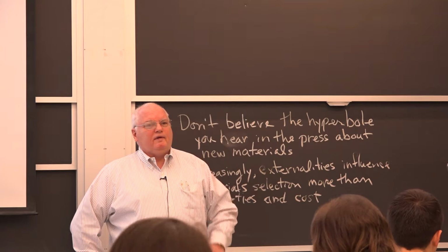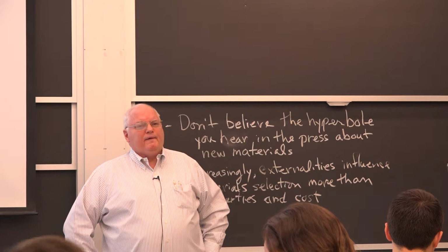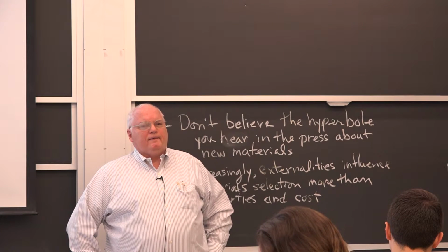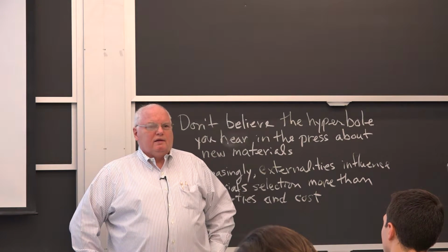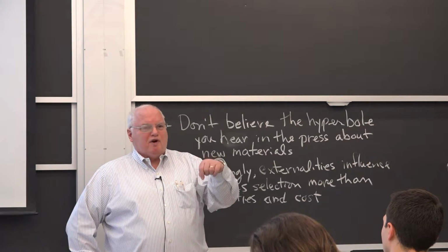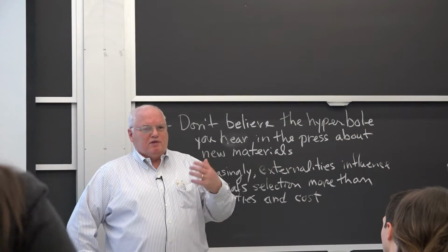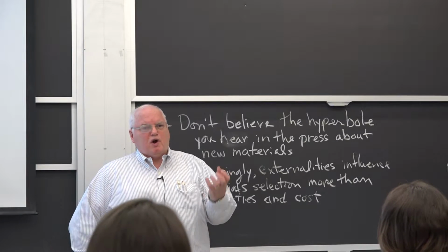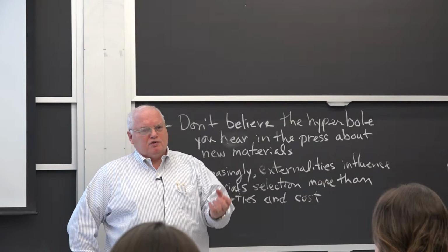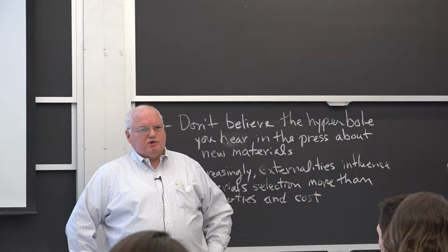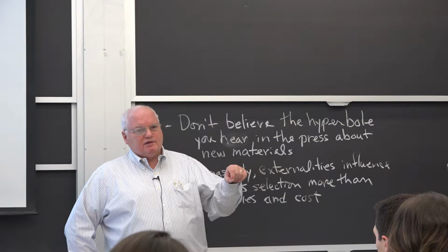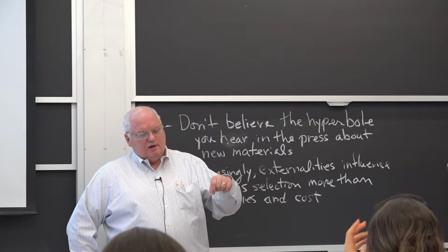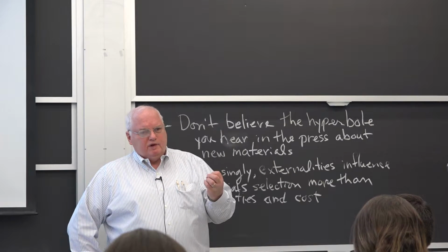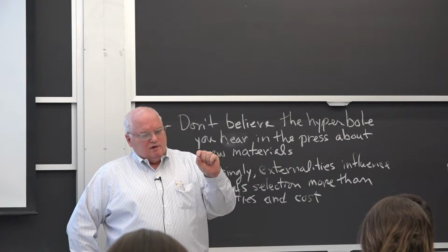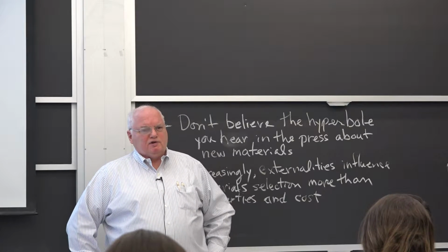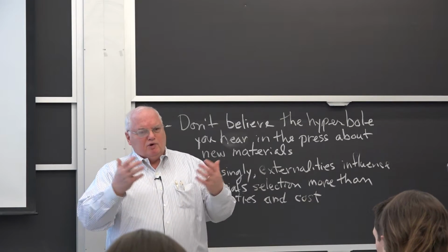Yeah? I was wondering, is there any issue with directionality with 3D printing of metals like there is with plastic? The orientation of the part matters a great deal. Only in terms of gravity, okay? I mean, but there's no structure like the wood structure, an anisotropic, if that's what you're talking about, because it's basically a bunch of little castings. And because of the high thermal conductivity, it's a little sphere that solidifies. You don't get a lot of columnar growth and things like that.